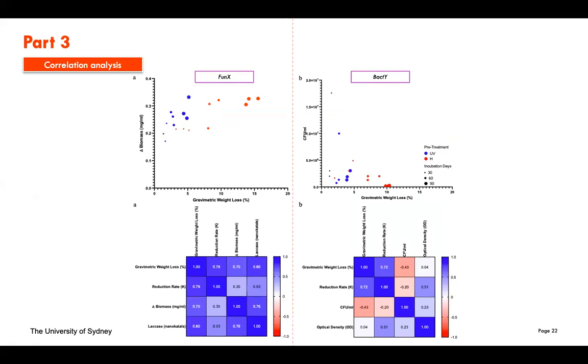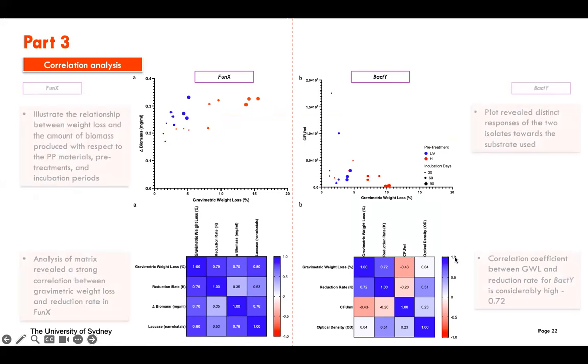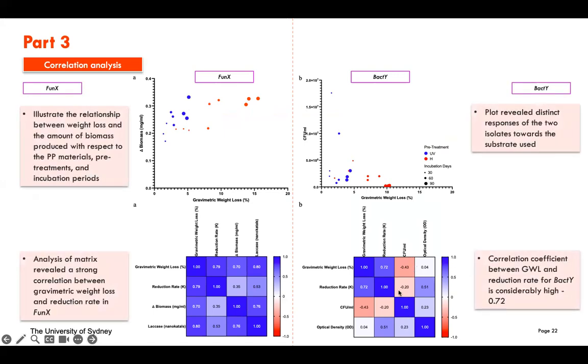And the same thing, we also did the correlation analysis. We want to see which one is the highest. The heat treatment will be the highest, and the lowest will be the UV treatment. But for the bacterial isolate, you can see that there are some negative correlations. The negative correlation here means that the weight loss and the bacterial count do not have a strong relationship, because the bacterial count declines after 45 and 60 days, but the weight loss somehow increased, only a little bit. So the correlation is not strong in terms of how the bacteria live and how much weight loss we got.